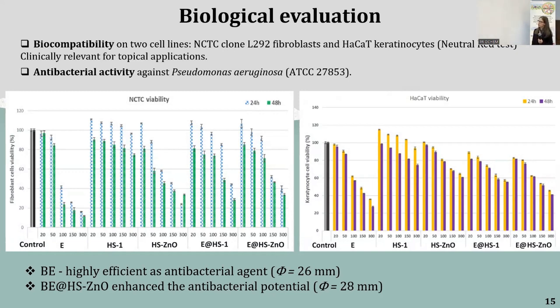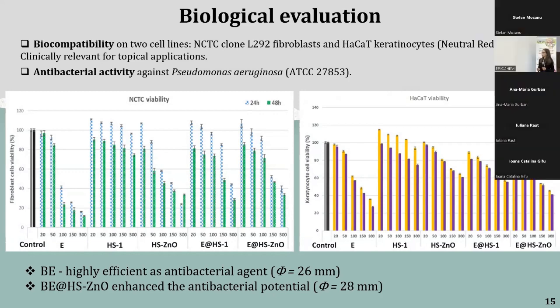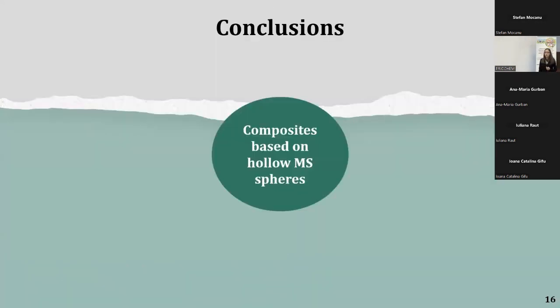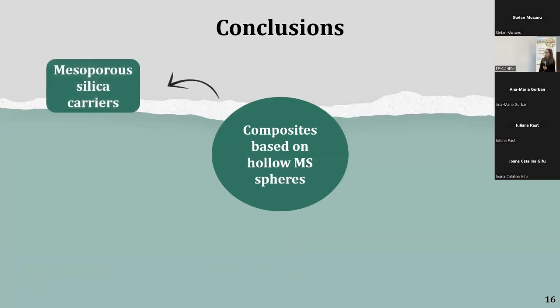The bilberry leaves extract proved to be highly efficient as an antibacterial agent, showing an inhibition average diameter of 26 millimeters. And furthermore, when zinc oxide was encapsulated, they slightly enhanced the antibacterial potential, showing an inhibition average diameter of 28 millimeters. In conclusion, this work was based on obtaining composite materials from mesoporous silica spheres.